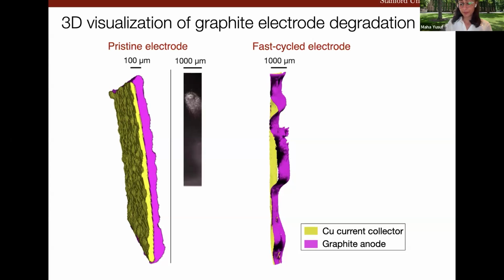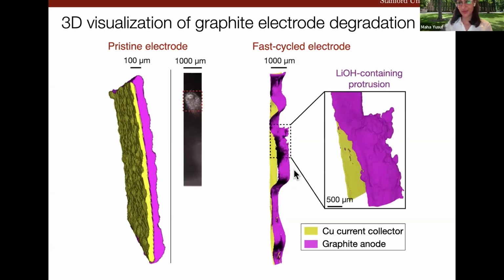We can also see this giant lithium-containing protrusion, which can be directly correlated to this whitish deposit that I showed you a few slides ago, right? On this graphite, which was part of a battery pouch cell that was cycled to death. So you can see here that using simultaneous neutron and X-ray tomography, we were able to visualize lithium and a copper current collector at the same time.